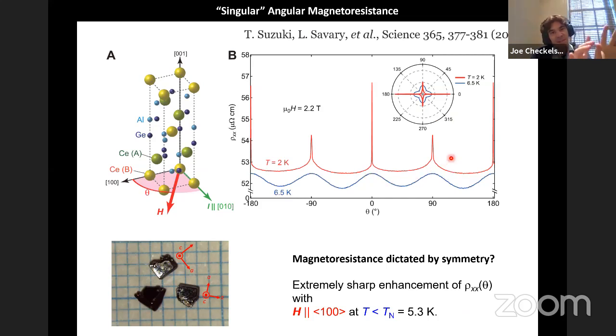So this is a different magnetic structure, but here, because you're just above magnetic ordering, you're kind of pushing the moment around. And so you can sort of see the scale of that effect. And so it's just that this effect from the domains is something that happens on top of that. But being able to image the domains would be a super important aspect of proving that.